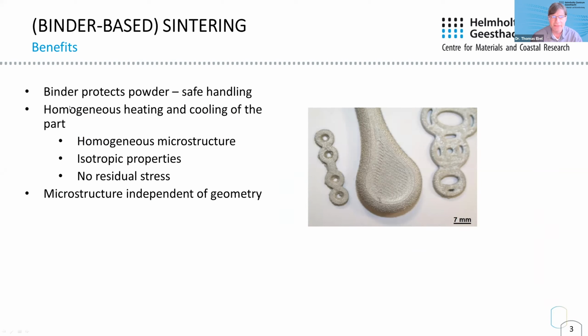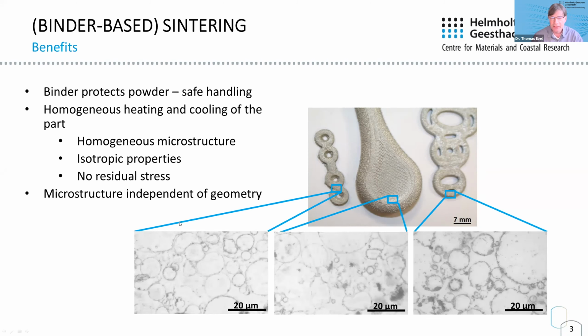The advantage we see in the sintering process is that the material gets a very homogeneous heating and cooling. So the entire part gets the same heat treatment, which results in an absolutely homogeneous microstructure, isotropic mechanical properties, and no stress after the sintering. Furthermore, what is very nice is that the microstructure itself is independent of geometry. So it doesn't matter if you process a small part with a thin wall or a thicker wall, you always get the same microstructure.